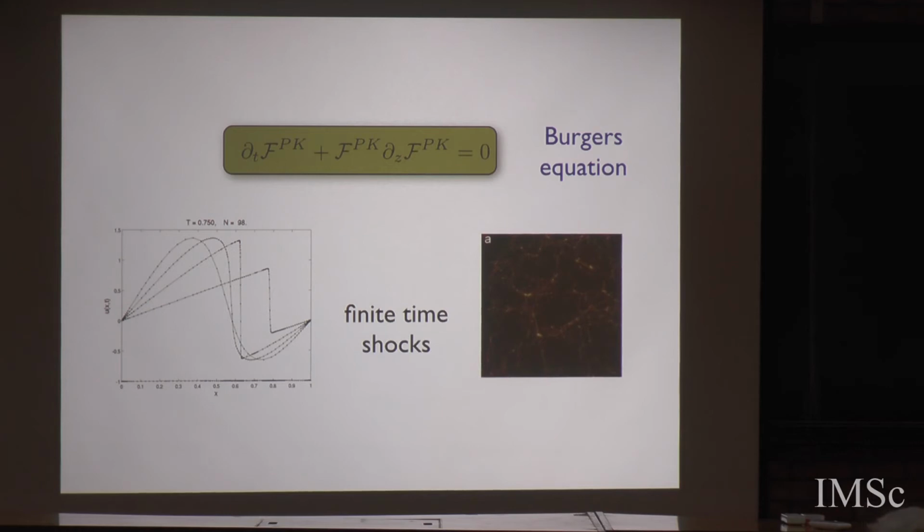So what does it tell you? It tells you that the process of dislocations coming together and forming grain boundaries is nothing but the production of shocks. A grain boundary, which is just a concentration of lots and lots of dislocations in a tiny region, is just a shock. It's a shock front.